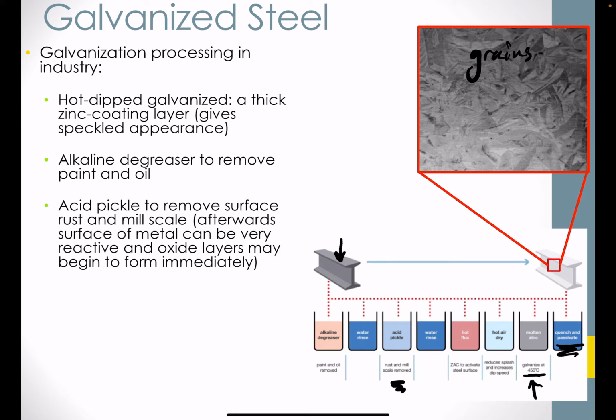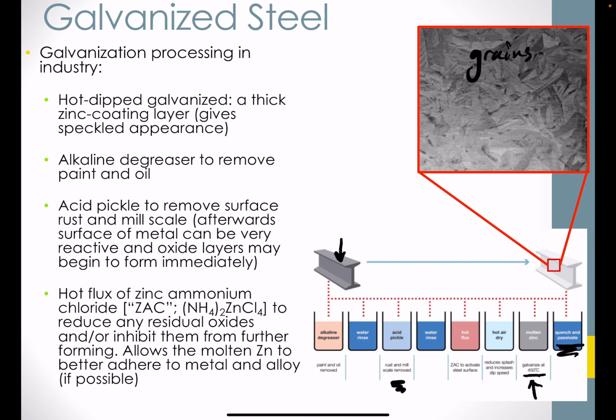Okay, and after this acid step, the surface is very reactive. It will rapidly generate new oxide layers as it resides in air. So transitioning the material from the acid pickle to the sort of hot flux step in minimum amounts of time is advantageous. And so this hot flux of ZAC, zinc ammonium chloride, formula shown here, allows for the application of a very thin coating of zinc to be applied to the surface and to handle any residual oxides that are forming. So this acts as a bit of a zinc priming step to allow the additional zinc of the hot melt step to really bond to an alike surface that is already containing some zinc.